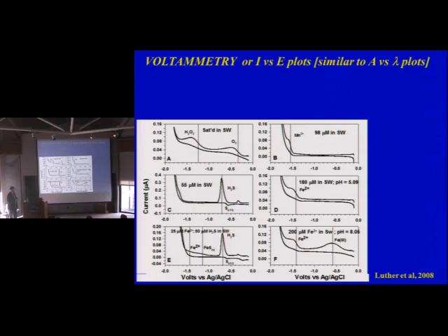In the long run here, what we're going to do is scan from a somewhat positive potential, minus 0.1 volt, negatively to minus 1.8, and then back. This is what oxygen in seawater looks like. It also looks like that in freshwater. This system works in freshwater as well. So we don't have any problems with salinity changes. It doesn't work in deionized water. You need at least a little bit of salt to make everything go.